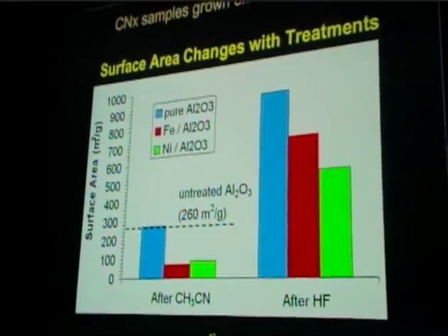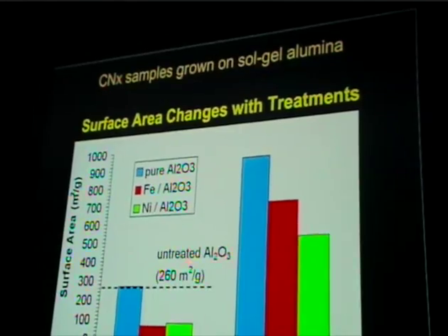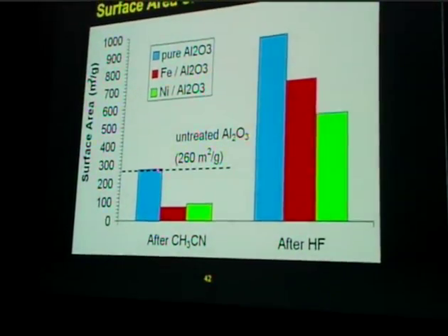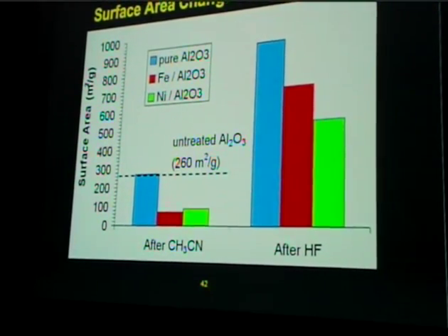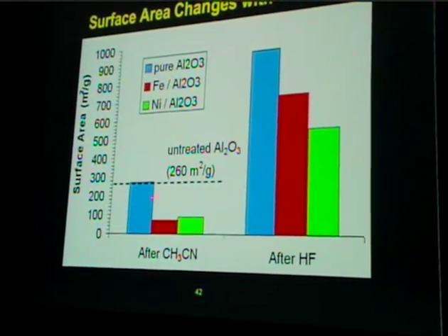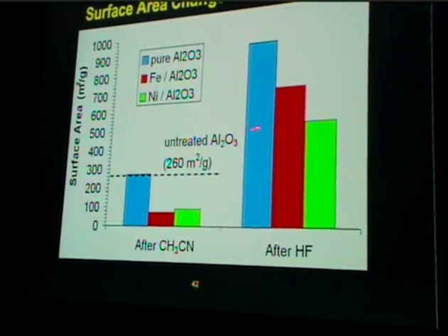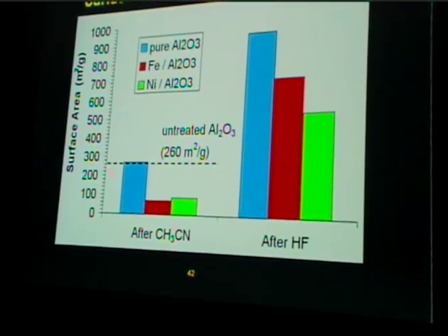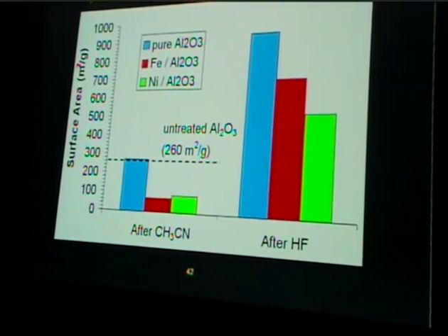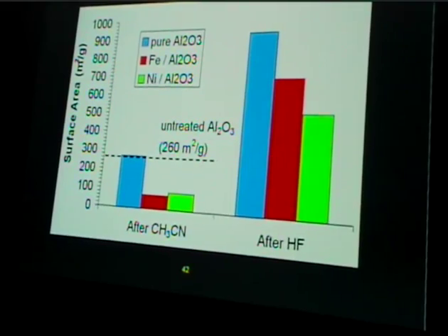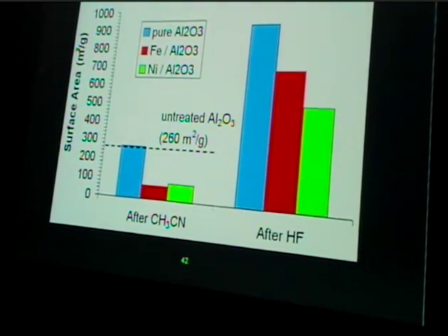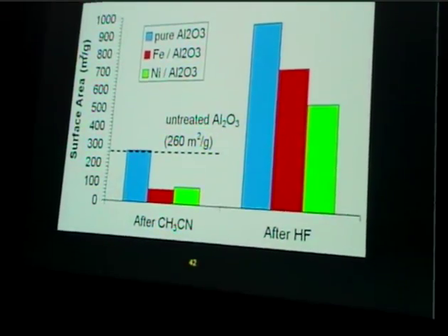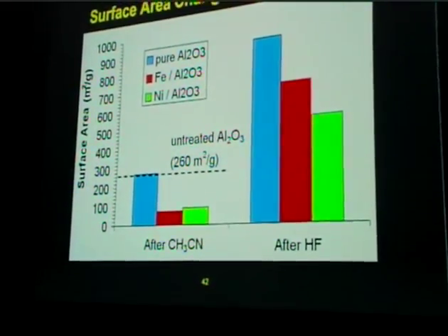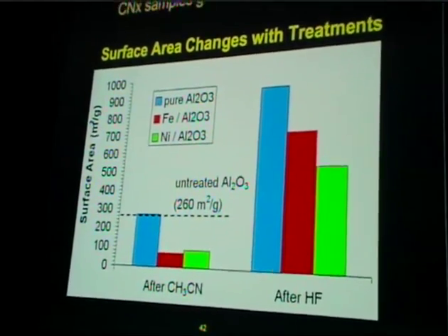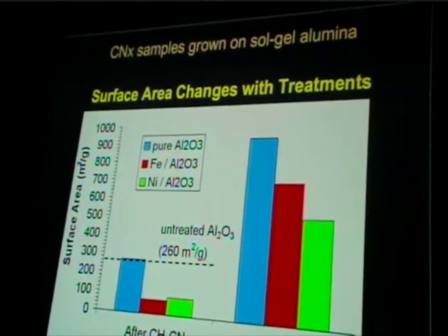If we look at the surface areas, these are the untreated alumina after the acetonitrile pyrolysis. And this is the surface area after the washing. And you can clearly see that we are getting very, very high surface areas over these materials which are grown on sol gel alumina, and after pyrolysis of acetonitrile have been washed using hydrofluoric acid to get rid of all of the alumina and the metal present.